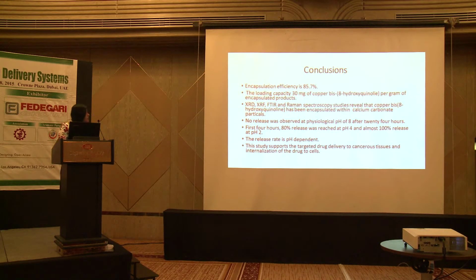My conclusion is, encapsulation efficiency is 85.7%. The loading capacity is 30 mg of copper bis-8-hydroxyquinoline per gram of encapsulated product. XRD, XRF, FTIR and Raman spectroscopy studies reveal that copper bis-8-hydroxyquinoline has been encapsulated within the calcium carbonate particles.